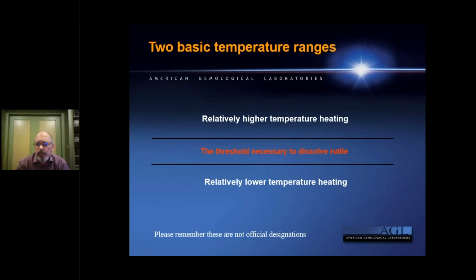I've been speaking about it for more than 10 years now, and that's really, you have two essential temperature ranges when you're talking about heating corundum. You have relatively higher temperatures and you have relatively lower temperature heating. And the threshold in between this I use is that threshold necessary to dissolve rutile silk. So again, this is not a fixed point, this is not a fixed temperature because there are different variables which will impact when rutile begins to dissolve.